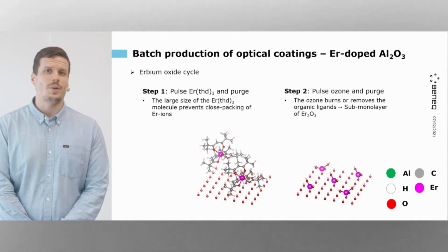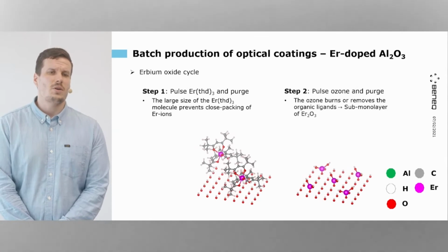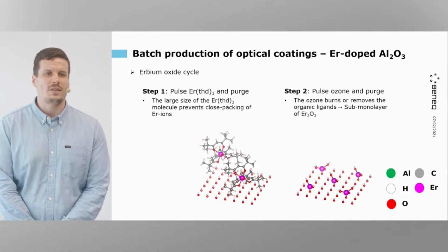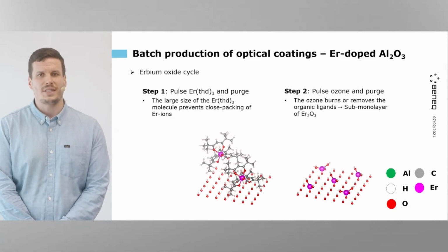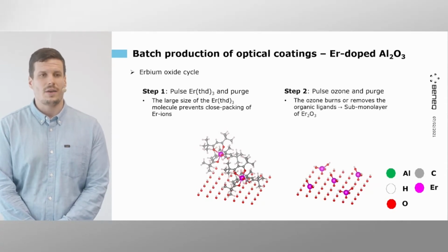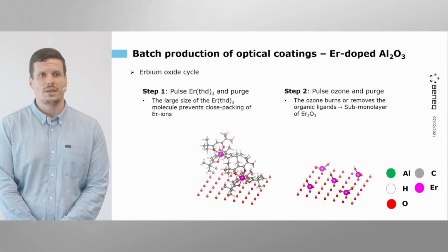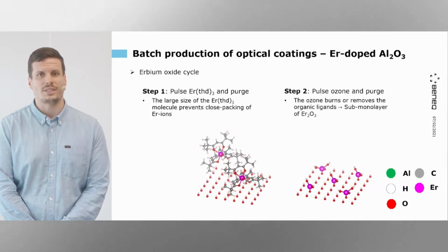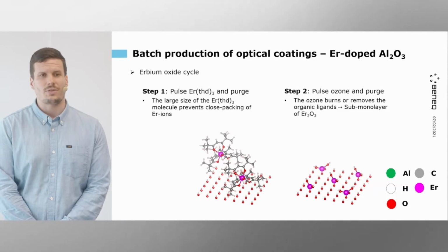But why is this so important? It's because ideally in a laser crystal, one needs to have a sufficient separation between the dopant atoms. Otherwise, they will just re-emit and reabsorb all the outgoing photons in your system, which leads to very decreased efficiency.